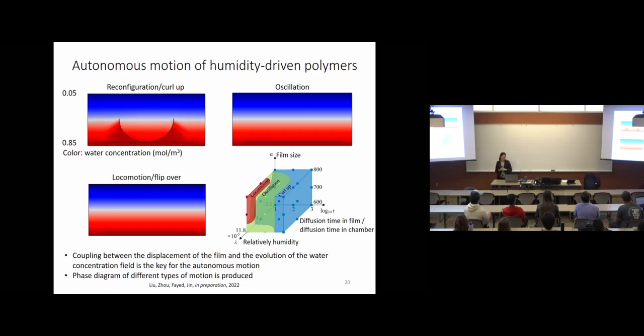Then let's see some simulation we have obtained. In the first case, we obtained this reconfiguration. And in the second case, we indeed observe this crazy oscillation. Those are the observations in this phase diagram when we change different regions of the phase diagram, when we change relative humidity, film size, and the material diffusion time scale versus the diffusion time scale in the chamber. The third behavior is this flipping over. This is a simulation in COMSOL. We combine solid mechanics and dilute species together. We need to use this arbitrary Lagrangian-Eulerian configuration because it's sort of like coupling solid and liquid together.